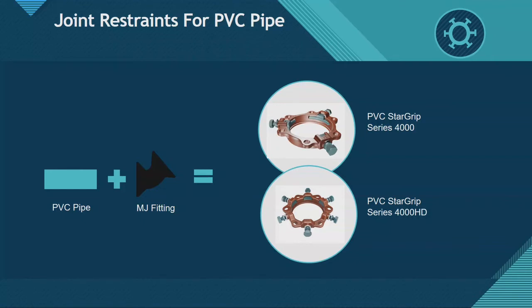The reason is that the pipe is a lot more compressible, so as you tighten those T-bolts, you will start pushing that gasket into the pipe more, and it'll just kind of make the pipe into an hourglass kind of shape. So reduce it. 75 to 90 foot-pounds for standard PVC. Ours is 55 to 65 foot-pounds for a PVCO. But depending whose restraint you're using, you want to check with the manufacturer what their recommendations are if you are using PVCO pipe.